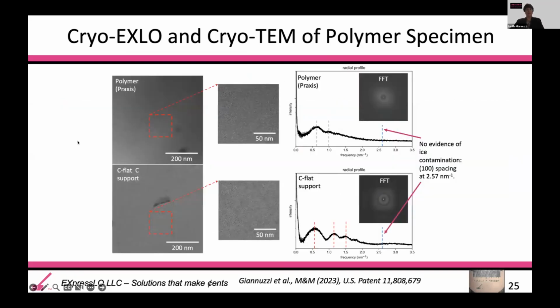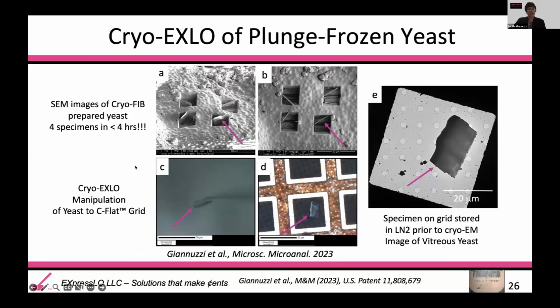But if we take a close look at the FFTs of both the polymer sample and just the support film itself, we see no evidence of ice contamination in the FFT. So we know then that the transfer process worked and there was no contamination.